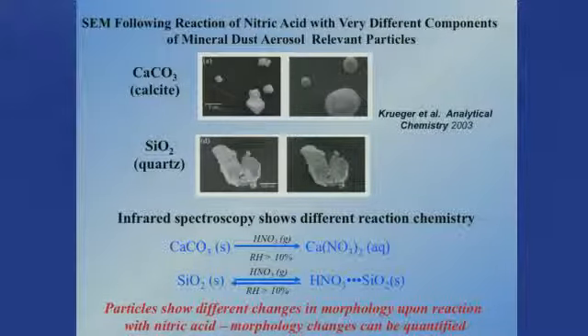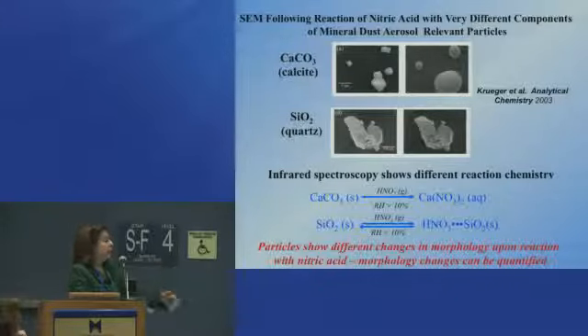Basically, a solid particle starts to look like a liquid droplet due to the heterogeneous chemistry of nitric acid in the gas phase. We've studied this reaction in great detail, and I don't want to talk too much about it, except to say that we were able to use different techniques, including infrared spectroscopy, to show we were making calcium nitrate, which forms a deliquescent layer and was able to pick up water. And we were able to monitor that chemistry in great detail. As Kim talked about, the importance of soluble species on the surface can affect cloud condensation nuclei activity, and we've shown that this reaction can affect that activity. In the case of the quartz, what we found when we did our IR studies is you get nitric acid molecularly, very weakly adsorbing on the particle surface, and that reaction is a reversible reaction, and so we were able to really nail down the chemistry, both from a microscopic single particle level and then looking at the chemistry in more detail with some bulk powders.